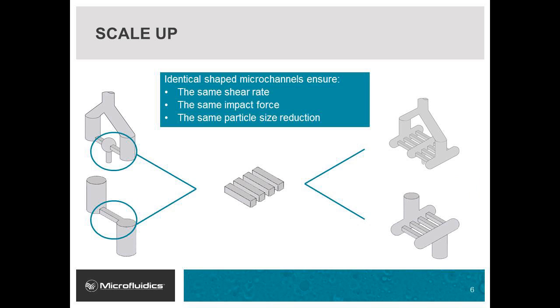The other benefit of these interaction chambers is that since they're so small, typically in the range of about 100 microns, we can array them in parallel for scale up. So you do your developments with a single microchannel, and then when you go to scale up, we just use a larger pump and align multiple microchannels in parallel, and that way you get the exact same velocities, the exact same shear rates, the exact same energy dissipations on the production scale, and virtually always we're able to generate the same particle size distribution on the production scale that we were able to generate on the lab scale.